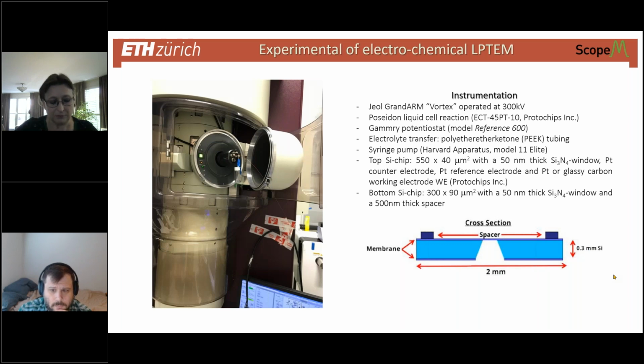And it was, of course, where we used STEM. Just an insider hint: if you do electro studies in TEM and you have a big gas bubble blocking the view, you don't have an image. It's black. I switch to STEM and, very carefully, without moving the specimen from the corner, I just push this bubble. I hit the thing locally, you induce a convection, and the bubble shifts. It worked quite a few times. It really helped, and it worked.